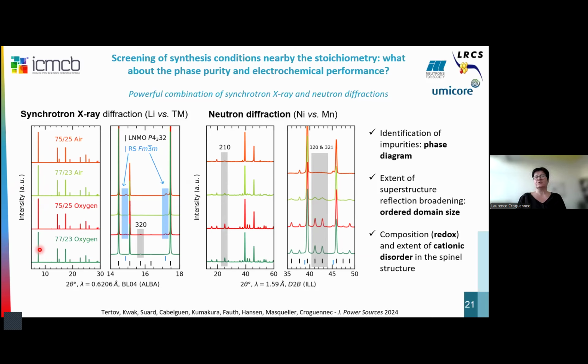So when we use synchrotron X-ray, of course, we can distinguish lithium versus transition metal ions, but we cannot distinguish nickel and manganese. And you can see also that using synchrotron, we are really able to detect very tiny peaks. So here in blue, it highlights peaks associated to a rock salt type impurity, nickel rich. But you can see that it highlights also already by X-ray a peak associated to an ordering between nickel and manganese. And so it already highlights that we have an ordering between nickel and manganese in at least these materials here that were obtained under oxygen.